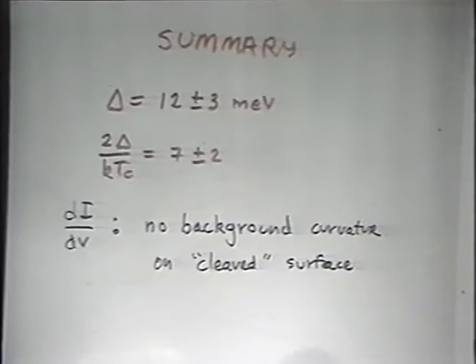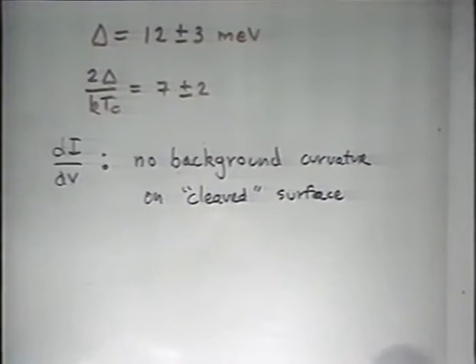So, getting back to the beginning, our deltas from these curves are 12 plus minus 3 millivolts, 2 delta over KTC of 7 plus minus 2, and the DIDV shows no background curvature on a cleaved surface. Thank you.